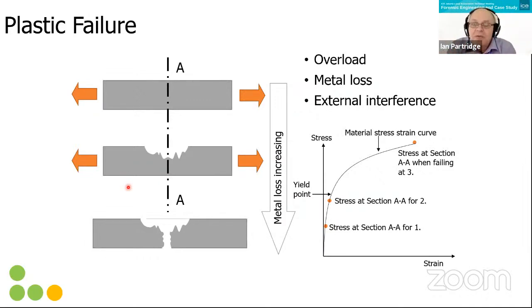First is the plastic type of failure, which is what at degree level and college level we're taught that we're designing to allow for, so the material properties don't get overloaded. So one way to fail is to actually increase the load till it fails. The other way is to reduce the section by metal loss, either by corrosion or by things like erosion or mechanical removal of the material. Things like external interference. So any of you that are in the transmission pipeline industry, external interference is a big issue. So you're reducing the section, upping the stress and overloading the section till failure occurs.